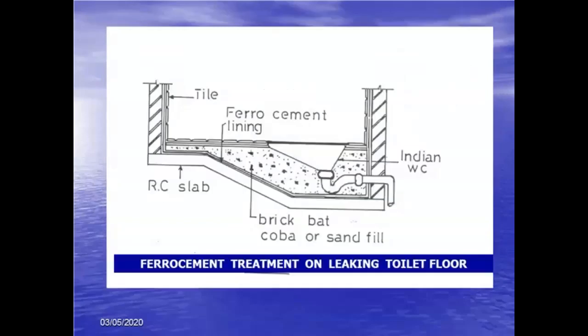A common problem is a depressed slab filled with water where water penetrates through improperly placed tiles, dampening the RCC slab — a very unhygienic condition visible from below. During construction itself, one layer of ferrocement lining can be applied over the existing RCC slab before sand filling and tile fixing, solving the major problem before it develops. For roof treatment, no skeletal steel is needed — only square woven mesh or chicken wire mesh, acting like a plastic sheet covering the roof completely, preventing water entry without removing the existing weathering coat.